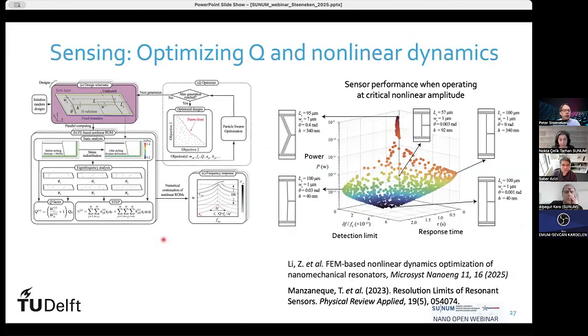This optimization of resonators is also important for other types of resonators. And you can, of course, do this with machine learning, but there are other optimization techniques like particle swarm optimization. And the nice thing about that is that you can optimize multiple parameters at the same time. So here we create a kind of model system, again a silicon nitride string, where we try to optimize the support of it. For a sensor, you would like to have it respond fast. You would like it to be able to detect very small signals, and you would like to operate it at very low power. So what we did is we created a finite element model that captured all these different parameters based on the geometry of the resonator.